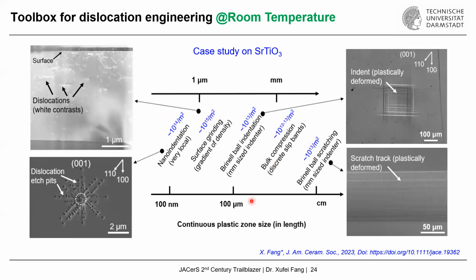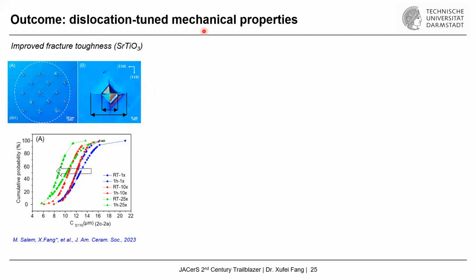So this actually gives us a very nice platform now to use the dislocations for what we mentioned at the very beginning, for the functional and mechanical studies. For instance, here, the dislocation-tuned mechanical properties, I focus on the improved fracture toughness in strontium titanate. So we first induce the dislocations, and then we put the Vickers indents into the plastic zone and see that the crack lengths actually start to decrease compared to the dislocation-free region. And this is a strong indication that the fracture toughness, or let's say the resistance to crack propagation, has been increased. And this is good news, of course, for ceramic materials.